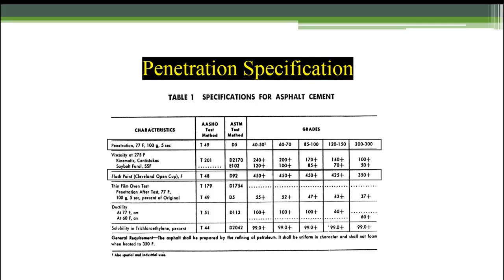So when you look at that on the far left side, the 40-50, that's a very stiff asphalt, isn't it? It barely penetrated into the top of that little tin of asphalt. You get over to the 200 and 300, guess what? High pen number means very soft asphalt. That needle was dropping down to the bottom of the can, so to speak.